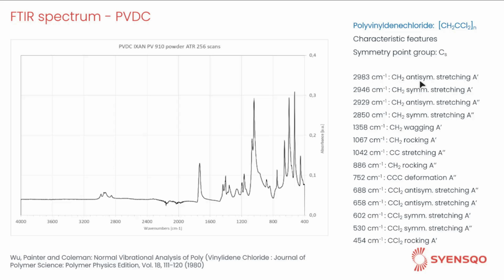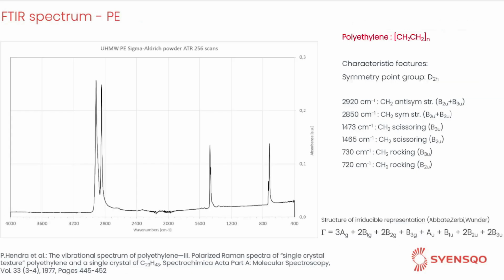On the left side, there are the indications of the normal modes that characterize this polymer structure, which regarding the polymer backbone, we have a quite low symmetry situation. The symmetry point group of the system is CS, so very low. In the region of the CH stretching, we can note at least two facts. The first one is that the intensities of the CH stretching are quite low. And the other one, that we'll see in more detail later, is that we have quite a complex structure and some frequencies in, let me say, the high frequency region of CH stretching are quite near to 3000 wave numbers.